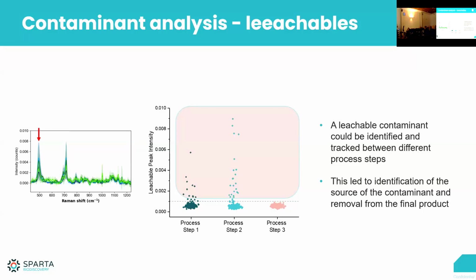This is a big advantage of having a holistic technique like SPARTA, because we can investigate things that we're not necessarily looking for. If you compare this with fluorescence-based techniques, no one is going to preemptively stain for silicone leachables in a formulation, or fluorescently stain cholesterol in LNPs, whilst we can see that there can be significant variation between those particles. We can look at it all at the same time. So we can quantify the amount of this, and we can also track it through different process steps, and they used a different tertiary cleanup procedure to get rid of these contaminants.